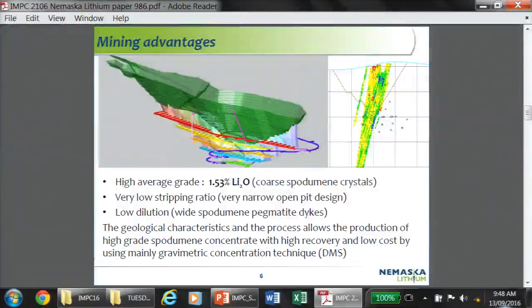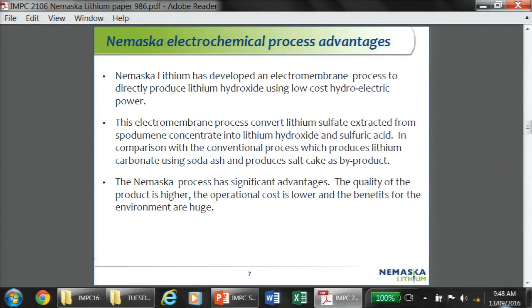If you don't manage that properly, if your spodumene deposit is not of high enough grade and the dike large enough to properly separate the waste from the valuable ore, then it can give you deep trouble and you won't be able to produce a good quality concentrate and transform it. So that's very important for the production of a good quality concentrate, from which you can extract the lithium properly with high recovery after.